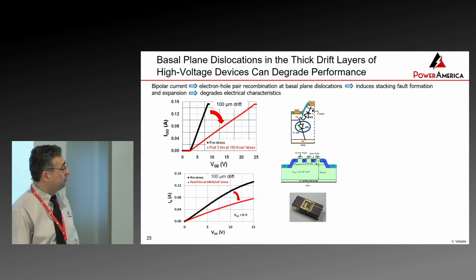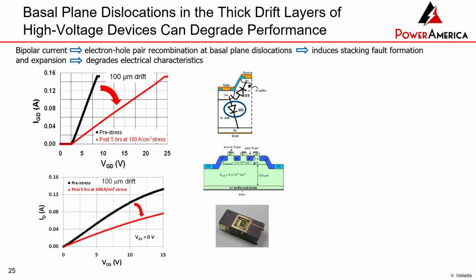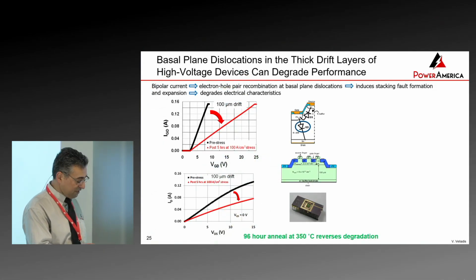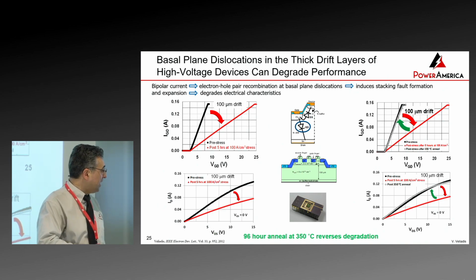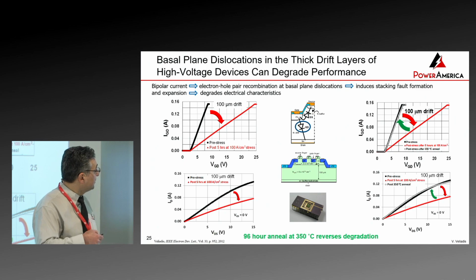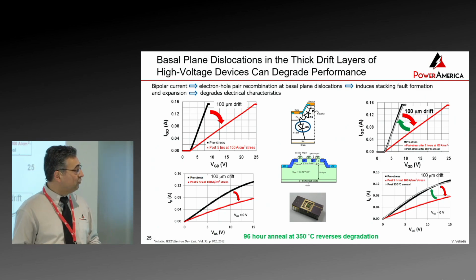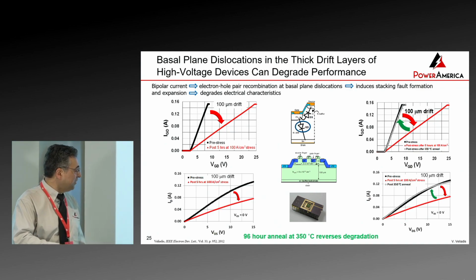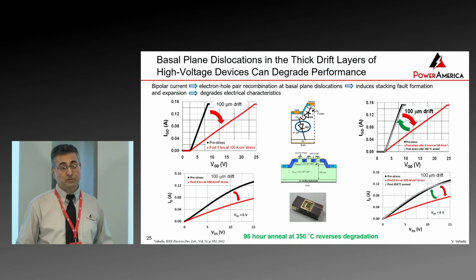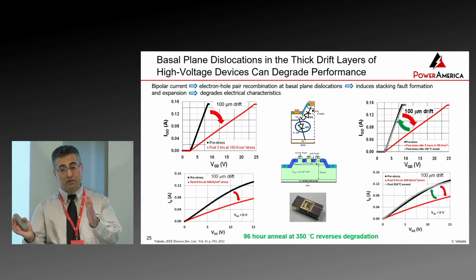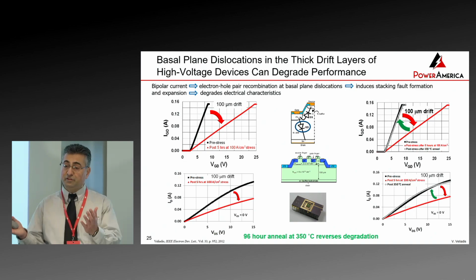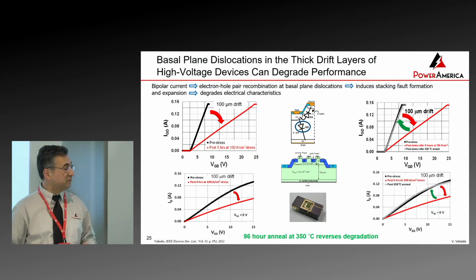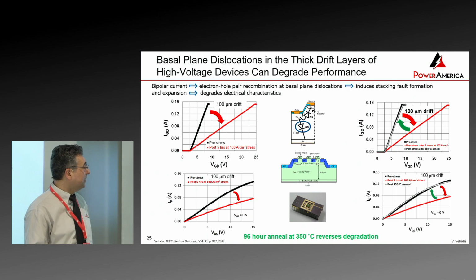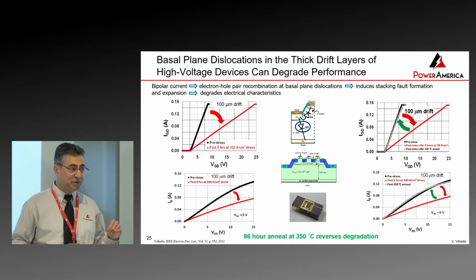Just an example of what the BPDs, the bipolar defects, will do. This is a device. The minute I bias it, it drops here, okay? And it stabilizes here, and same thing right here. So that's undesirable. That's what you don't want. Interestingly enough, in those days when I was playing around in the lab, I took this device. It has BPDs. The BPDs led to degradation because the BPDs became stacking faults with energy. And then I went ahead and annealed the device for 96 hours at 350, and the device went back to the original state. So you have BPDs, you give them energy, they become stacking faults that compromise the performance of the device. You anneal the device, the stacking faults shrink back to the original state. Okay, of course, that's not a mode of operation. You don't want to be doing that. But BPDs are still there, and it's actually the last kind of big defect that we want to get rid of.